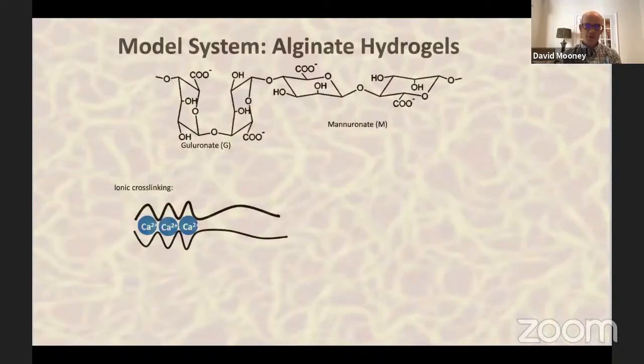So to explore this, we've been using a particular model system that I'll describe a little bit here. And it is a polysaccharide called alginate that is a block copolymer comprised of two types of sugars, which I'll abbreviate as G sugars or M sugars. And these are organized into blocks. The relevance of this block structure is that only the G blocks can actually participate in cross-linking, or formation of a hydrogel from these polymers. And when these polymer chains cooperatively share divalent cations, such as calcium, between the G blocks of adjacent polymer chains, this induces gelation. The M blocks don't participate in this process.